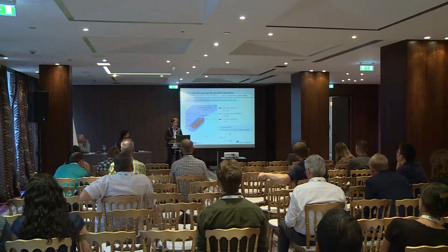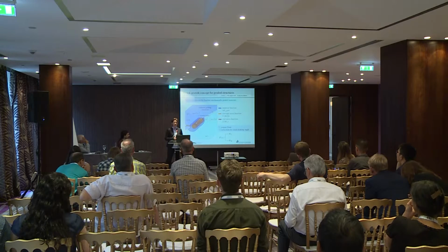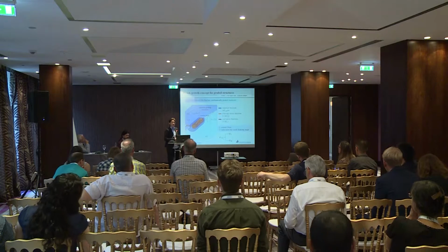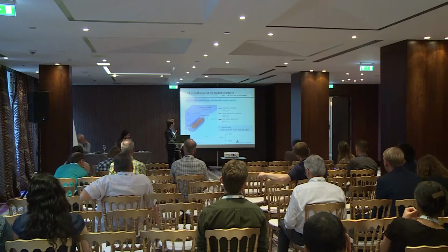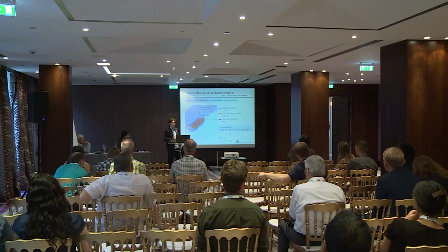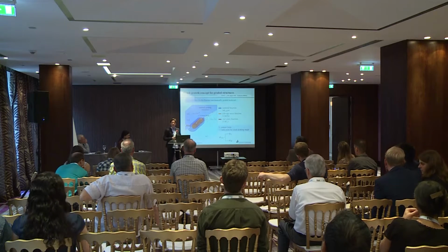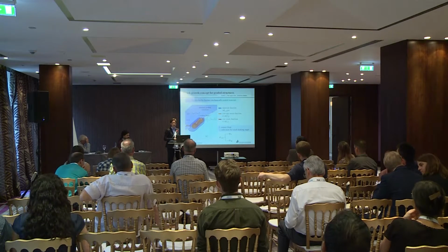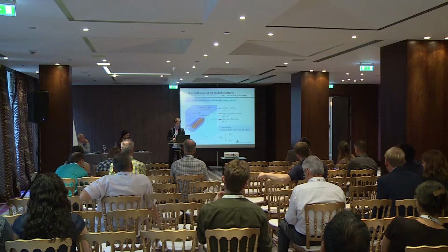So when I've got the material function and the relevant stress function, I also need to know what is really happening at the crack front. Therefore, I need to calculate the real stress using the stress intensity factor K. As you can see, it is shown in red for this crack front. As soon as this red function is greater than the orange one, the relevant one, then I know that in this situation, with a load applied, there will be some kind of crack growth. If it's not greater, then the crack will stop. There won't be any kind of crack growth at all.